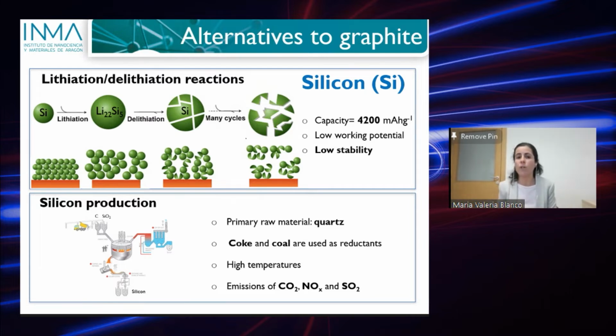Regarding how this silicon is produced, normally one of the industrial ways to produce silicon is by mixing coke or coal and quartz, and then applying really high temperature treatments. And this again gives emissions of CO2, NOx, solids and sulfur oxide. So I would say there are many things to improve in the production of silicon in order to have a really low carbon footprint, but also many things to improve in the engineering of silicon to get rid of these stability issues.